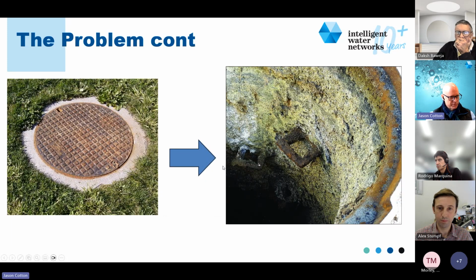The other side to this problem, and this is where we're focusing with Smartcrete, is that along the network, obviously these maintenance holes, they are a natural area where there's a lot of headspace and air, and the hydrogen sulfide gas goes into that headspace. And so we get significant degradation of these maintenance holes. And of course, this is where trucks drive over, people walk over, etc. So you get a truck driving over that, as you can see there, that's going to collapse pretty quickly.